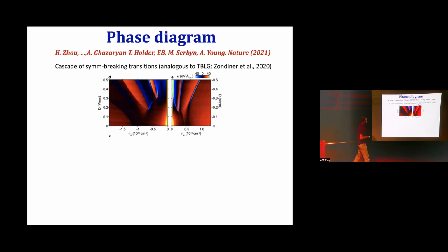This is an experiment by Andrea Young's group. He's mapping here the phase diagram of the system as a function of density of either electrons or holes, positive or negative, and displacement field, varying the electron dispersion. And he's measuring basically the electronic compressibility of the system. It doesn't matter exactly how he does that, but the important thing is that as a function of density and displacement field, you see these very sharp features. These features are transitions between different electronic phases, where the system spontaneously breaks symmetry between the spins, spin up and spin down.